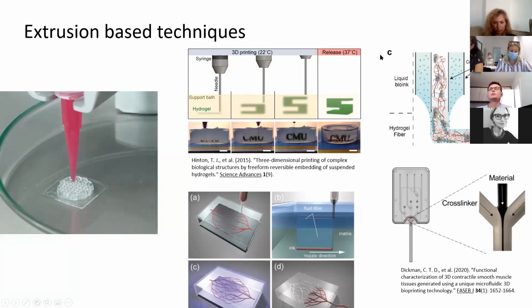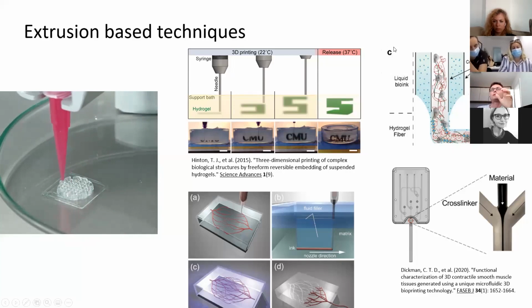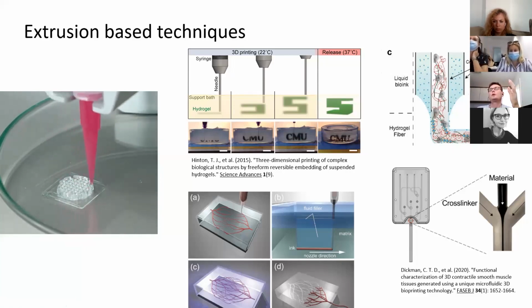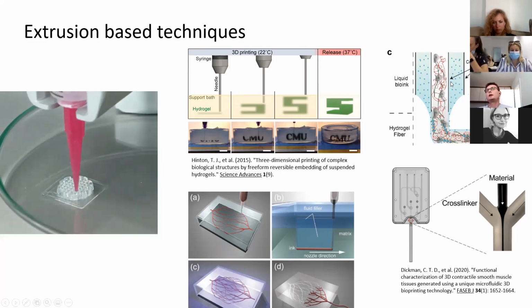And it's also possible with extrusion-based techniques to combine it with microfluidics or with more complex nozzles that will allow you to make tubular structures in one step. So, for example, here, if you take a look at the image, you have a coaxial or core-shell nozzle, you could also call it, where two materials are extruded at the same time. One is extruded through the inner nozzle and one through the outer nozzle, and then they cross-link at the interface. And depending on where you extrude the bioink, if it's in the middle, you stabilize it directly upon deposition. So even if it's liquid inside, it stabilizes at the tip of the nozzle. Or if you would invert it, so you would have the bioink in the outer nozzle, for example, then you could actually print a hollow tube in one step.